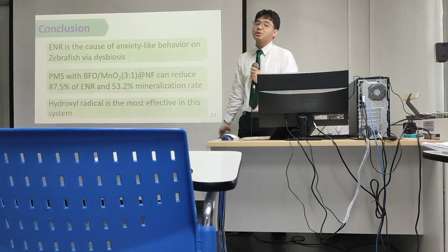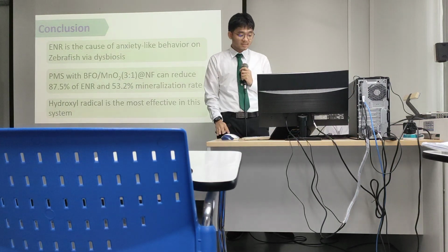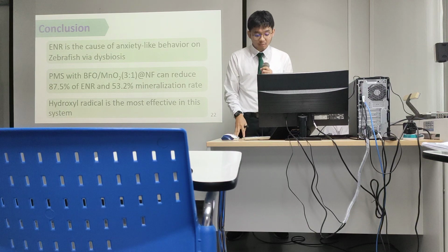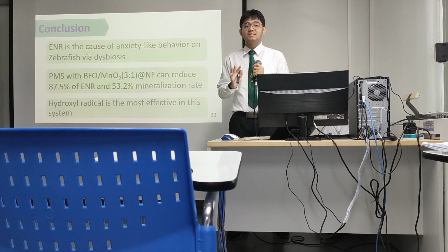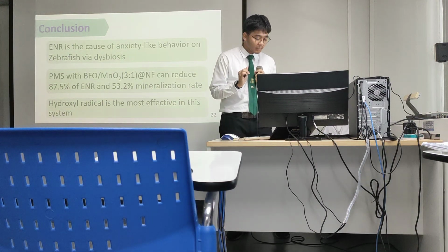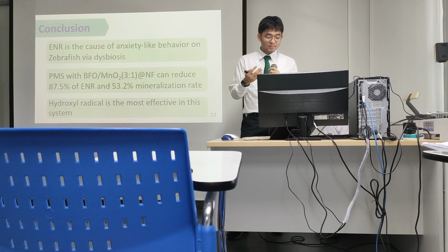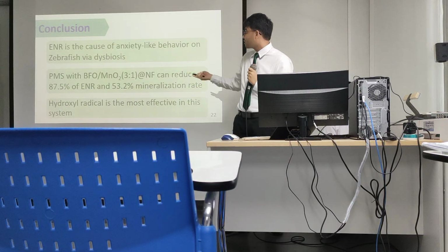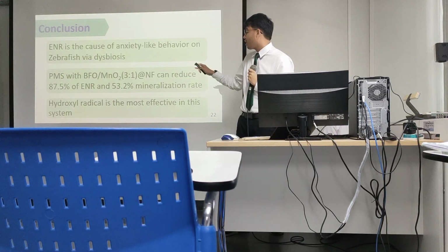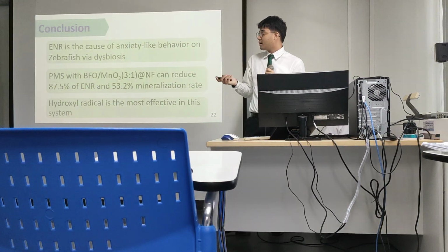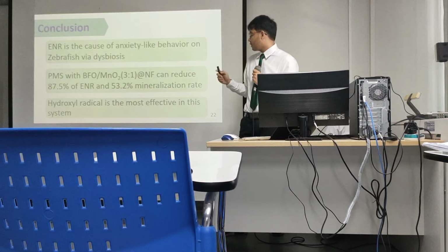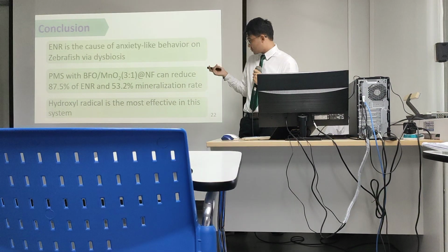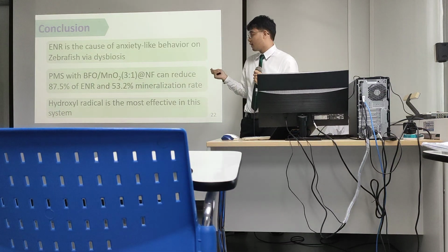For conclusions, enrofloxacin causes anxiety-like behavior in zebrafish, where dysbiosis affects the brain. Peroxymonosulfate with bismuth ferrite manganese dioxide at a 3 to 1 ratio on nickel foam can reduce 87.5% of enrofloxacin, and can mineralize 53.2%. And the hydroxyl radical is the most effective in this system.